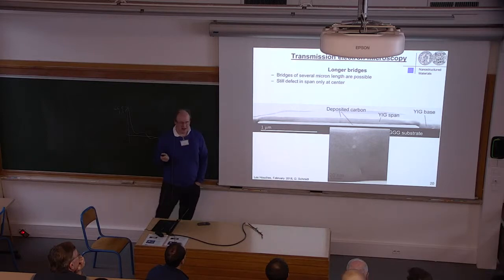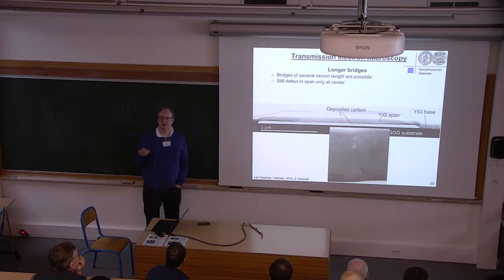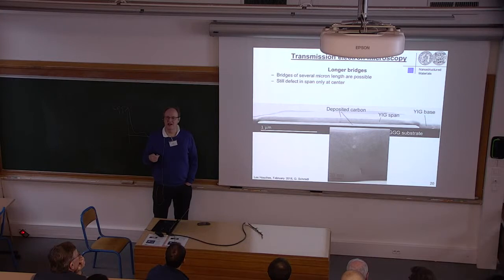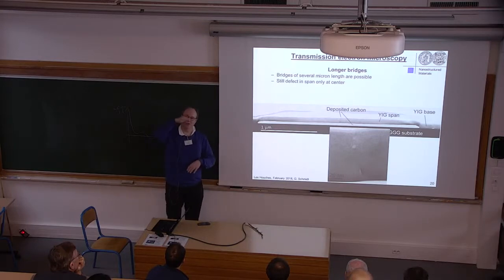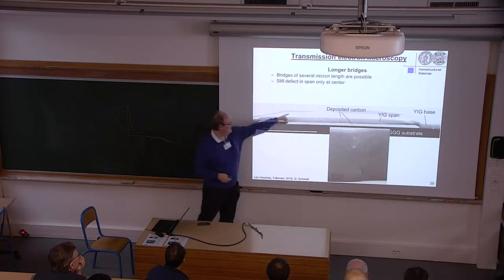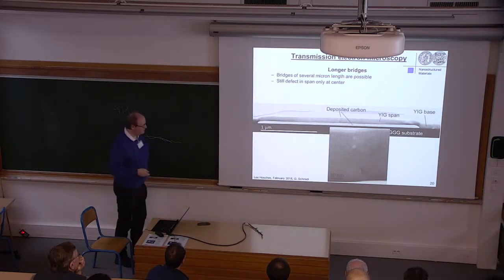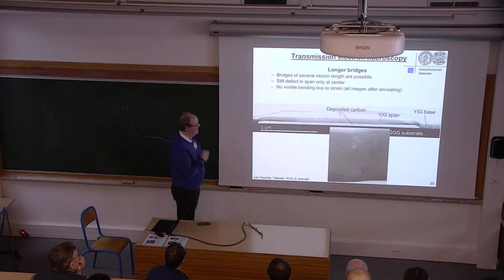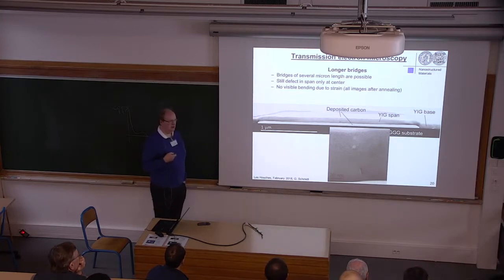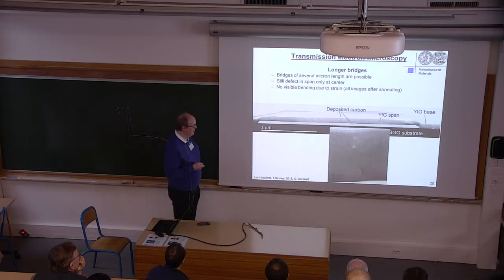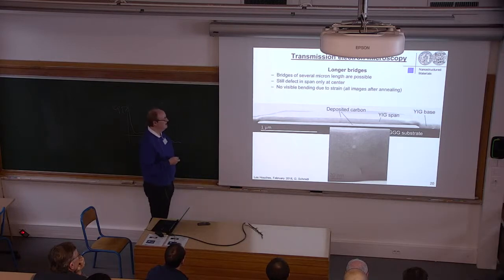These samples were prepared for transmission electron microscopy using focused ion beam, and to protect them, some carbon was deposited. As the electron beam, which leads to the deposition of the carbon, goes through the bridge, you deposit the carbon on top and on the bottom. So you have carbon here and you have carbon there. Anyway, now we know that we have this nice property, and again we have no visible bending due to the strain. All these pictures were taken after the annealing process. And here you can see, by the way, again the same defect as for the first structure. So long bridges don't matter at all.